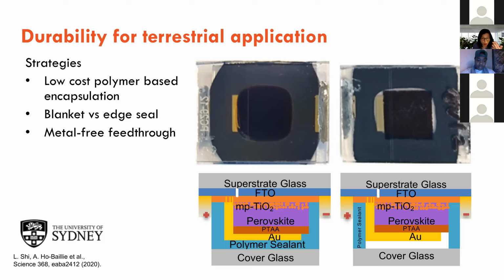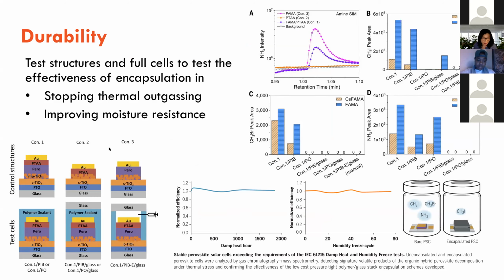And we use different ways of protecting the cell. Either we use the polymer as a blanket to completely cover the cell, or use it as edge sealant, so just put it on the edge to seal the two pieces of glass together. In this case, we rely on the FTO to conduct the current out, rather than using a physical metal wire. Anyway, we found the blanket approach is the best. We look at unprotected cells and also protected cells, and we can see that the protected ones have very, very low outgassing. So you can't see those signature products coming out.